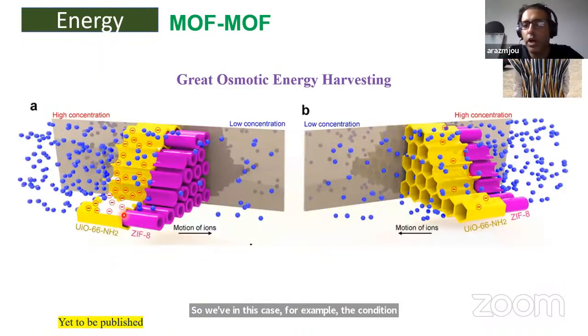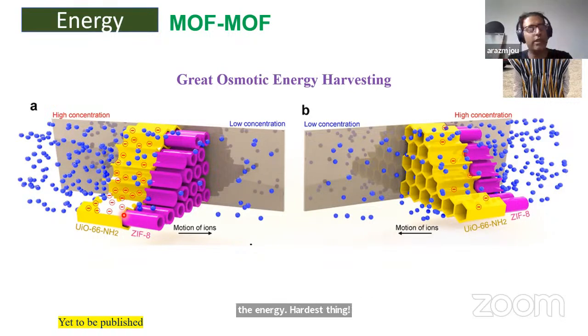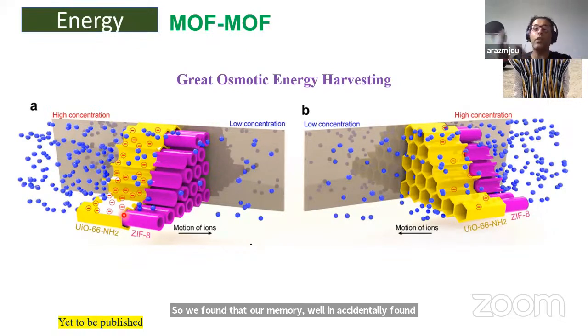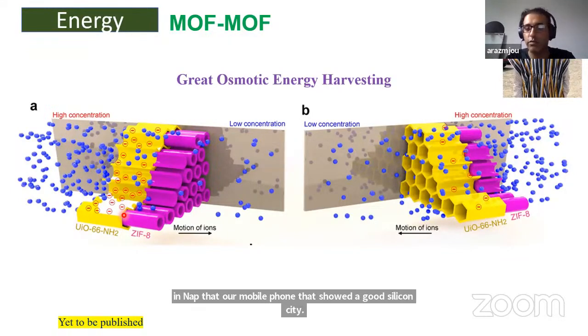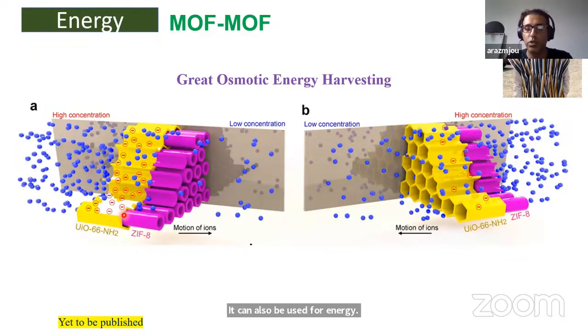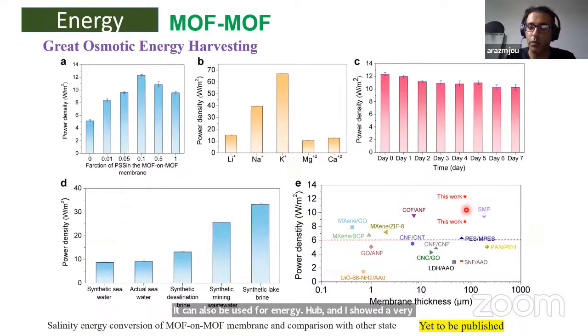In another work, one of our PhD students is working on using MOF-on-MOF membranes for osmotic energy harvesting. We accidentally found in the lab that our MOF-on-MOF membrane, which showed good lithium selectivity, can also be used for osmotic energy harvesting. It showed very good performance in terms of power density and producing energy.